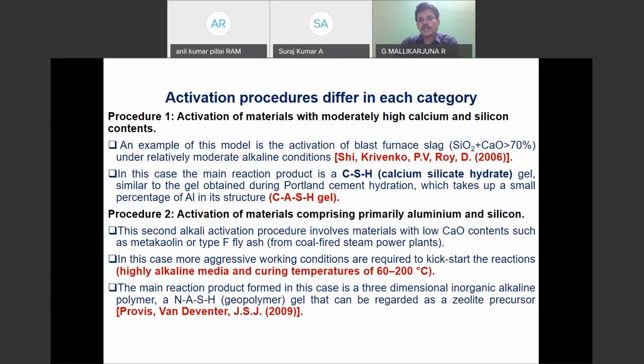If you take the high calcium, that is nothing but Portland cement or GGBS, the main reaction product formed is the calcium aluminum silicate hydrate gel along with the CSH gel. Whenever you take a larger amount of calcium source material for the activation, the concentration of sodium hydroxide can be reduced.